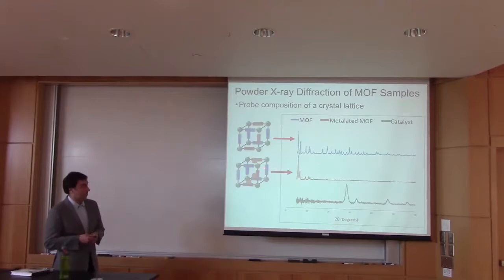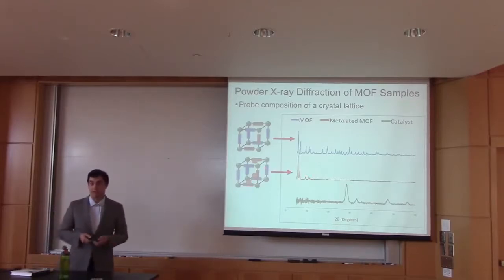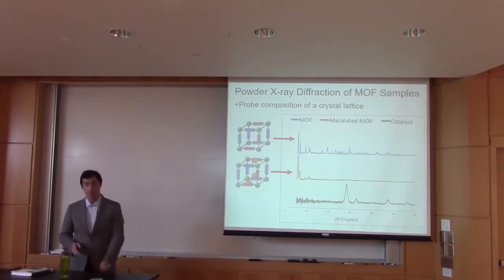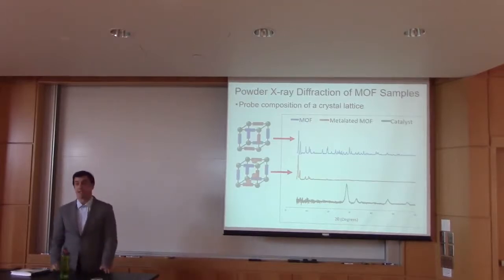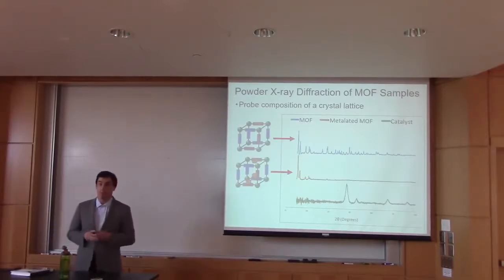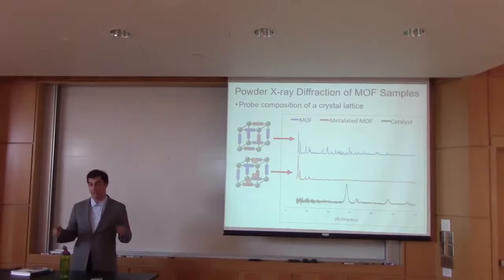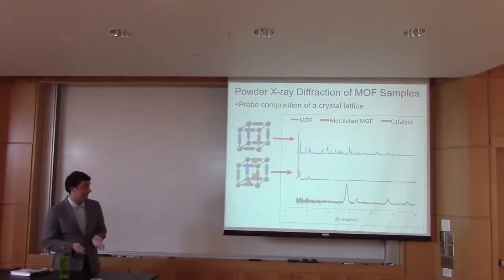And when we add the copper, we see the same crystallinity early on, but a suppression of the later peaks, which is fine. Maintaining the crystallinity is important here because we're trying to maintain a small copper oxide domain. And this indicates that we're maintaining that metal organic framework in that kind of even spacing once we've added the copper. So we should maintain smaller copper oxide domains and not have large ones form.